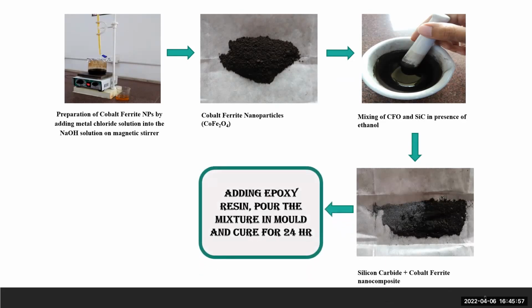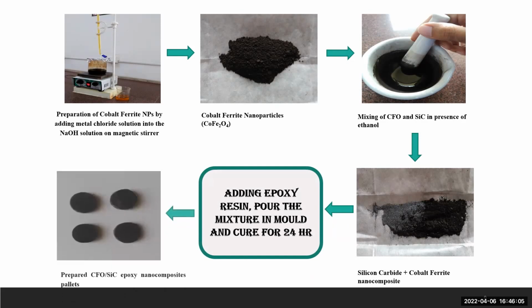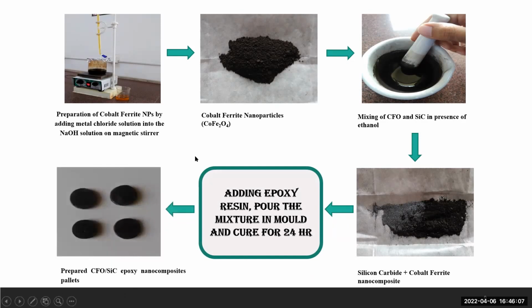Then we mixed this prepared sample with epoxy resin and poured the mixture into the mold, which was cured for 24 hours, and we get the cobalt ferrite silicon carbide epoxy nanocomposites in pellet form. So this process was carried out to prepare 4 pellets with different weight percent of silicon carbide, that is 20, 40, 60, and 80%, as you can see in this figure.